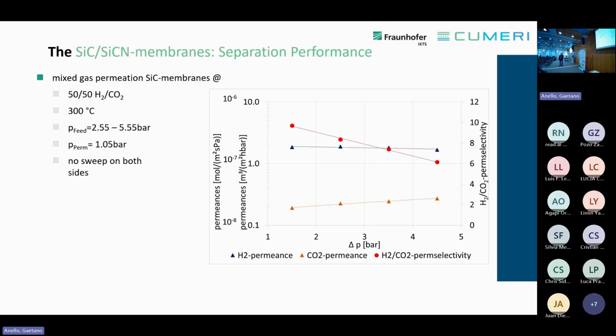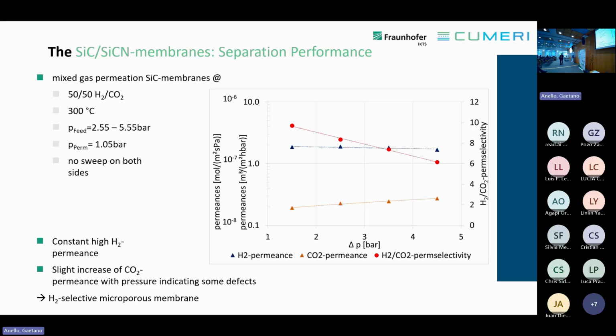However, with increasing pressure difference across the membrane, the hydrogen permeance kept constant, while the CO2 permeance increased slightly. Because of this, the selectivity decreased a little bit, but the initial value at 1.5 bar pressure difference was quite high, with a value of 10. Then it goes down to 6, but it's still quite okay for our separation task. The reason for the CO2 increase, we think, is that there are still some defects in the membrane. But it's a very nice hydrogen selective membrane.